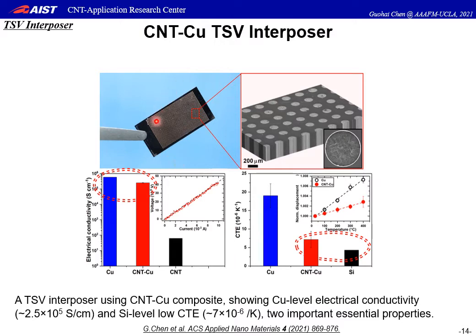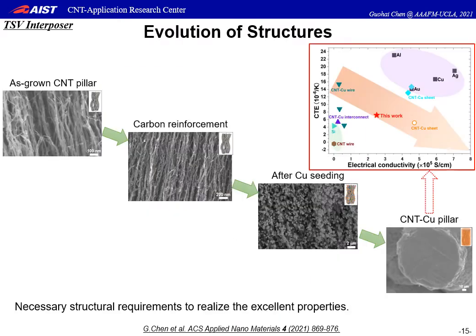This is the final product — freestanding well-ordered vias. The vias were nicely filled, as can be seen in a close-up SEM image. The interposer was measured with high electrical conductivity, about half that of copper. In addition, we also measured its thermal expansion. Interestingly, the interposer shows a much lower CTE than copper, but very close to silicon. This close match of CTE can help improve device lifetime by reducing internal strain due to the CTE difference between the via material and silicon substrate.